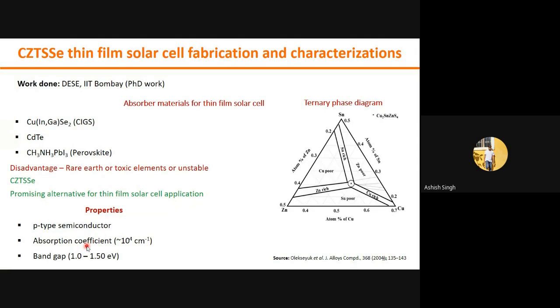This CZTSSe has an absorption coefficient in the range of 10 to the power 4 per centimeter. From this absorption coefficient, this absorber material can absorb maximum light in a film less than 1 micron thick, and the band gap can be tuned from 1 to 1.5 electron volt. And if we see the Shockley-Queisser limit, the maximum efficiency can be achieved at 1.45 electron volt, and that is 33% efficiency. So this material seems very promising for thin film solar cells, but it is not free from disadvantages.